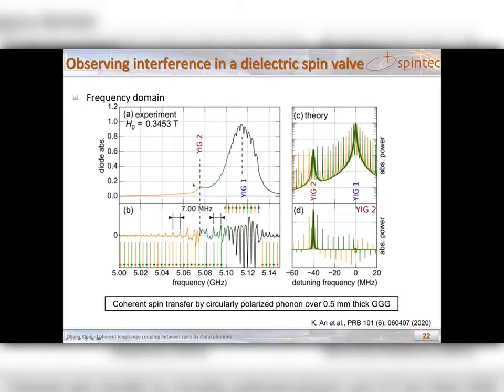Here YIG2 is on the left of YIG1. If we remove the broad background FMR, we can see the acoustic character better in this plot. So near YIG2, even phonons give larger absorption and less intensity for odd phonons, okay? And you get this double frequency of 7 MHz, so the odd phonons have almost disappeared in the vicinity of YIG2. This contrast inverts when you go on the other side of Kittel 2, okay, and it's now odd phonons that have constructive interference, while even phonons are destructive, okay.